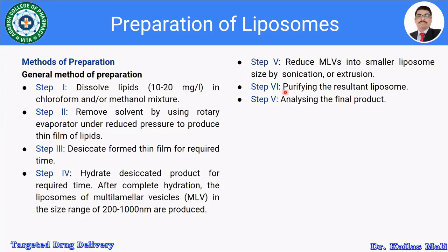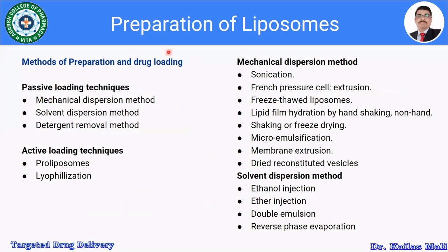Step six: purify the resultant liposomes — whatever contaminants are present need to be removed. The last step is to analyze the final product. These are the general steps widely used in the preparation of liposomes. Generally, drug is loaded in step one or step four: if the drug is lipid-soluble, dissolve the drug along with the lipids; if the drug is water-soluble, dissolve it into the hydrating buffer. Once the liposomes are formed, a suitable method is used to reduce the size of the multilamellar vesicles.